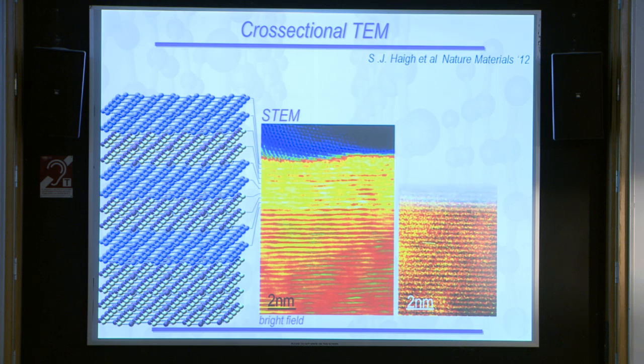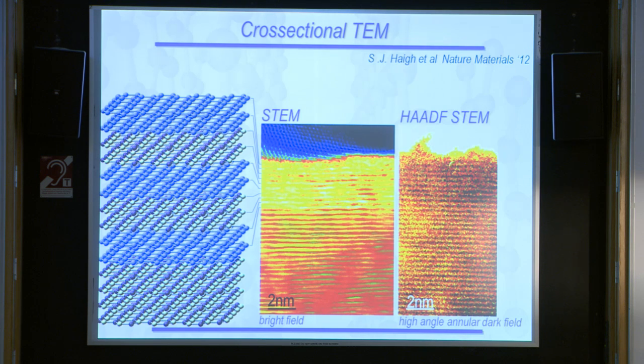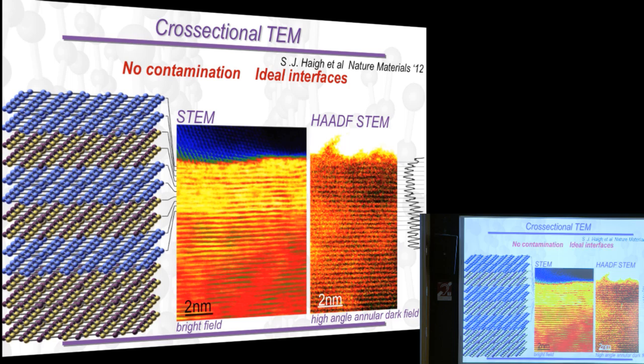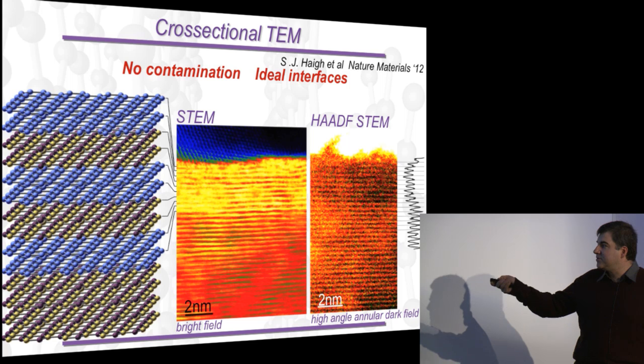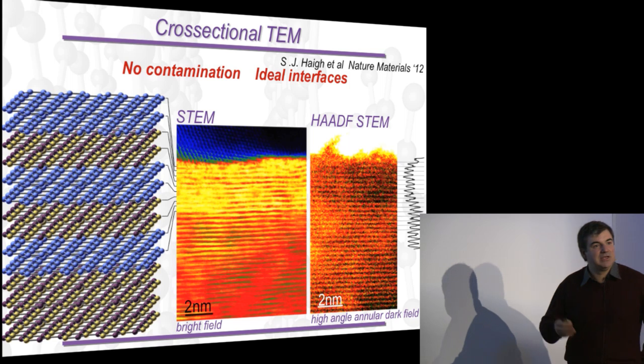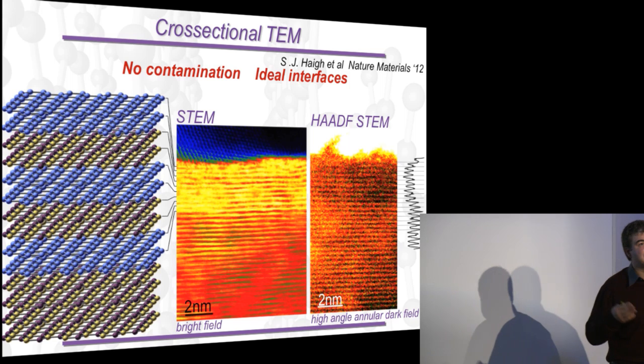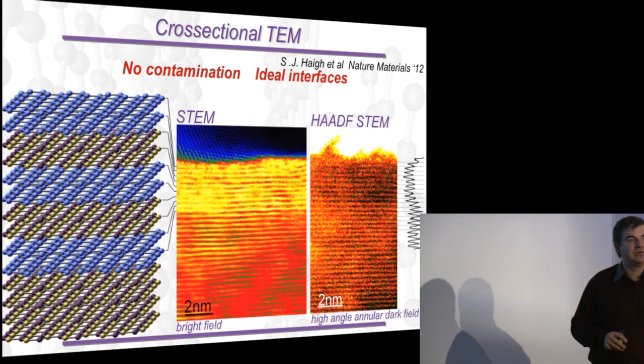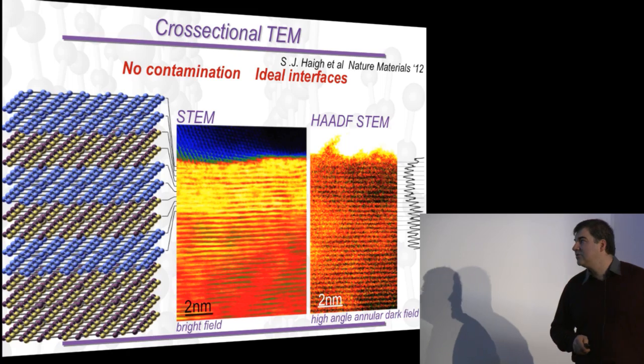But if you look at the dark field image of this, you won't notice where the underlying boron nitride stops and the layer of the heterostructure of graphene and boron nitride starts. So the periodicity is practically unperturbed. So the quality of those heterostructures is extremely high.